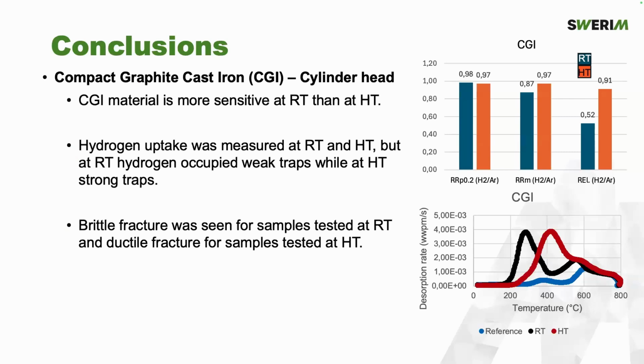I dig into conclusions. So, CGI, mainly used for cylinder head applications. It seems that it's more sensitive at room temperature than high temperature. Hydrogen uptake we measured at both testing conditions in terms of temperature, but we see a different distribution of hydrogen. We saw also brittle fracture at room temperature and ductile fracture at high temperature.